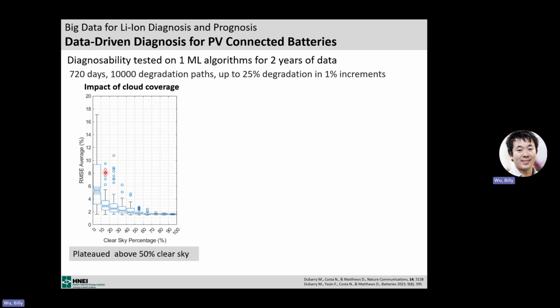And what we found is the average of the accuracy of a diagnosis, well, when there's no clear sky, it varies a lot. Some days you diagnose really, really well, some days it sucks. And if you have just constant low cloud, then it's not sunny, but it's pretty constant for the method to work. But if it's a lot of passing clouds, it doesn't work at all.